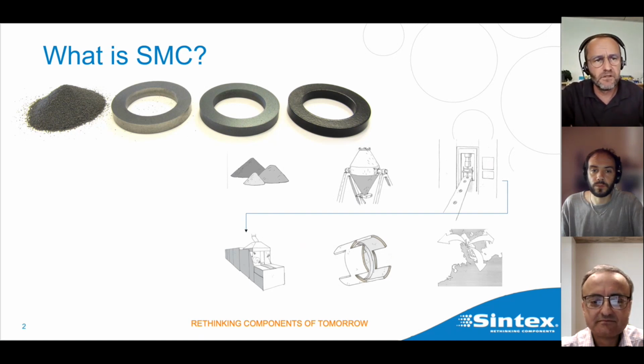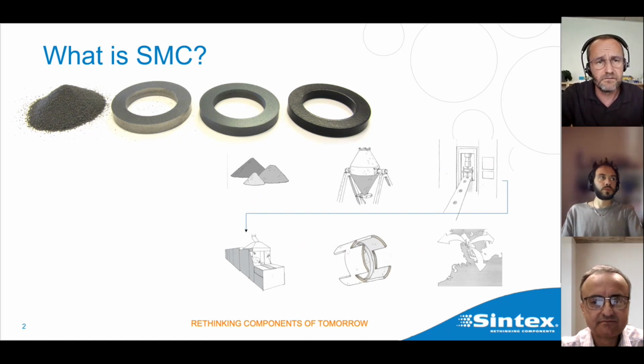SMC is a powder-based material. Every single powder particle is isolated. So it's like laminated sheet that is isolated on each side, but here, every particle is isolated, and typical particle size is around 100 micron. Those particles are then compacted into a part that is called a green part, and the green part is afterwards heat treated to have the final properties, both mechanically and magnetically. Afterwards, it can also be surface coated to have corrosion protection and so on.